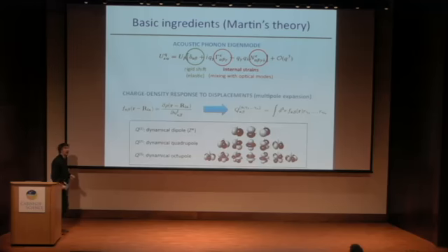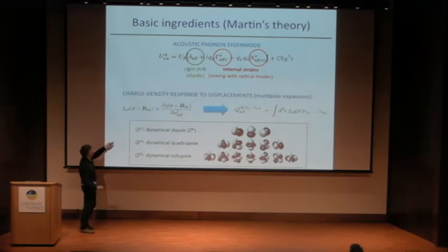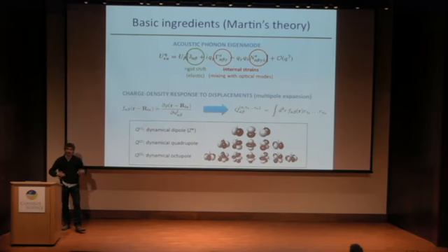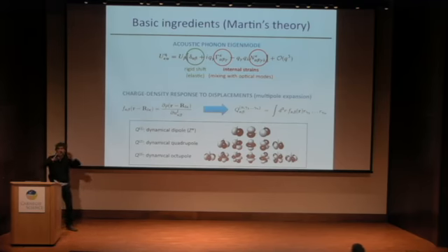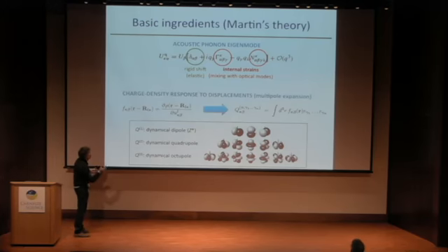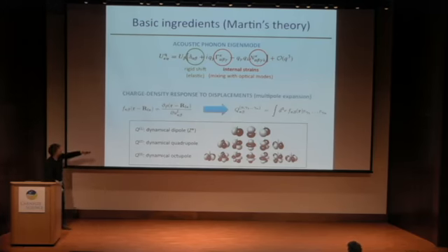And then, once you have these atomic displacements, it is not enough, because you need something that couples the displacements to the polarization. For this, the idea is based on Martin's theory of piezoelectricity, that consists in looking at the charge density response to the displacements of individual atoms. So you imagine the infinite crystal lattice, you displace one atom, this will induce a perturbation in the electronic charge, and you analyze this perturbation by expanding it in multipoles.